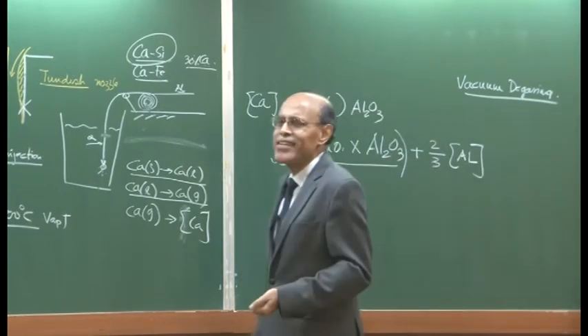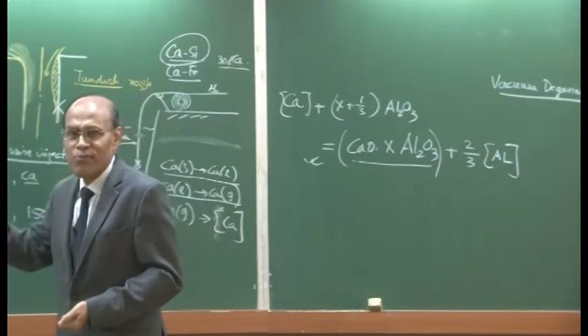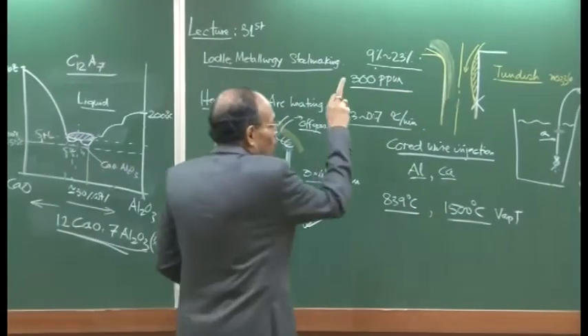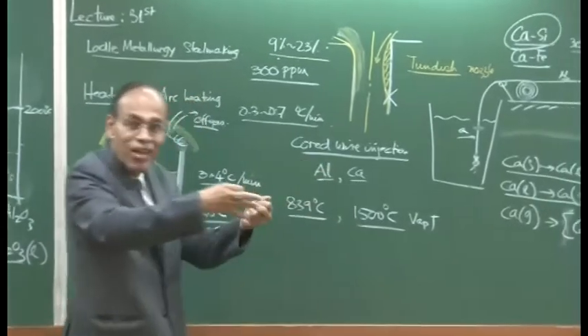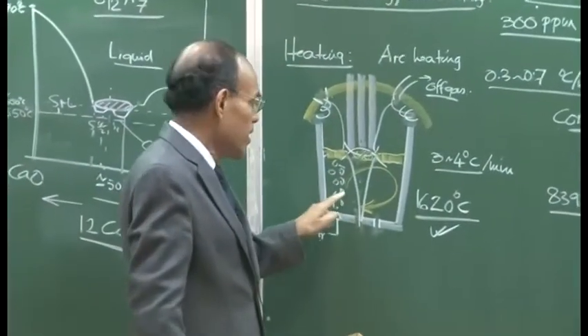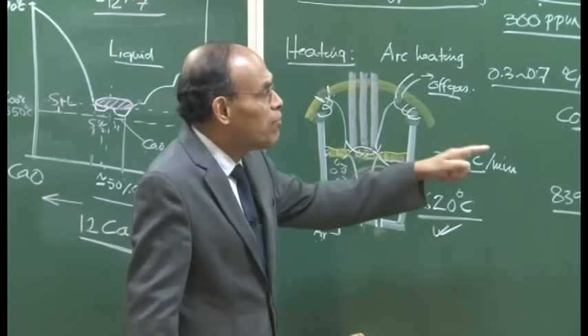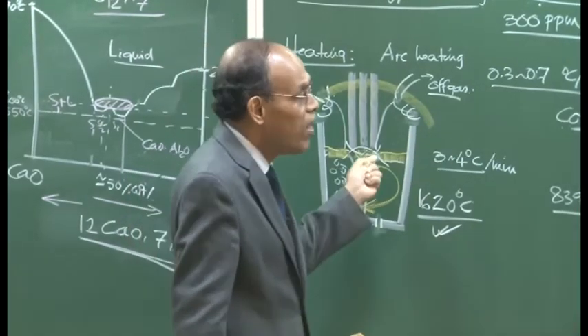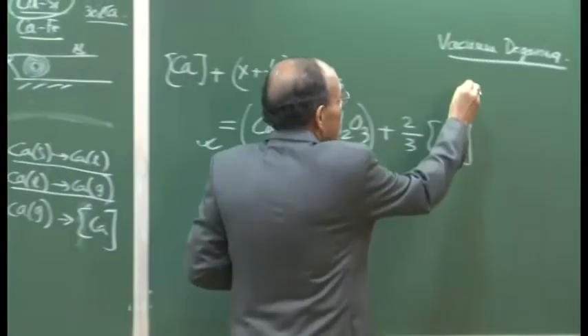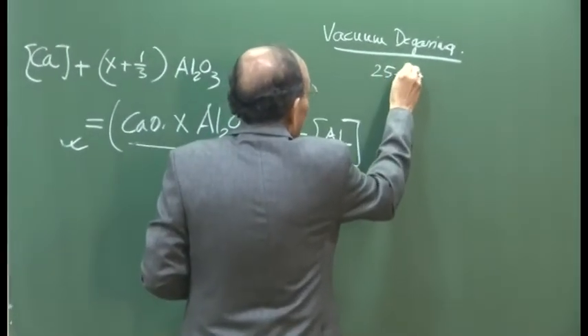And that is how it takes such a long time. We are doing one process after another: heating, deoxidation, then heating, then cold wire injection, then vacuum degassing. So, 20-30 minutes we have spent in heating only, okay? Another 10-15 minutes for this wire injection, etcetera. Then transportation comes, and then we take it to vacuum degassing, where again we can have 25-30 minutes of